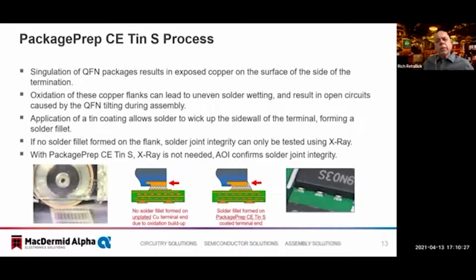Our package prep CE tin process is an immersion tin process that plates the exposed alloy leads after singulation. The immersion tin increases the solderability of the sidewall, allowing solder to wick up the side of the terminal. A solder fillet or foot is formed that can be detected and confirmed by AOI, and that eliminates the need for expensive and timely X-ray examination.